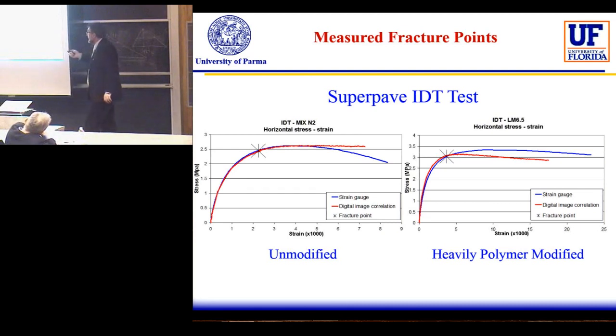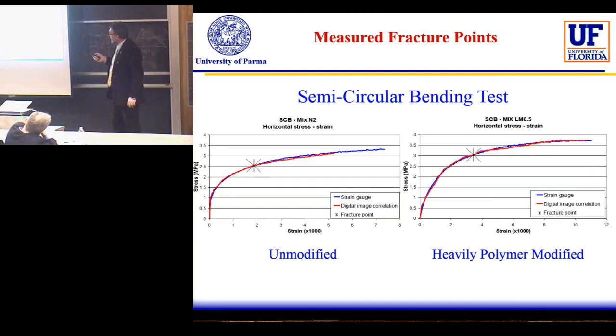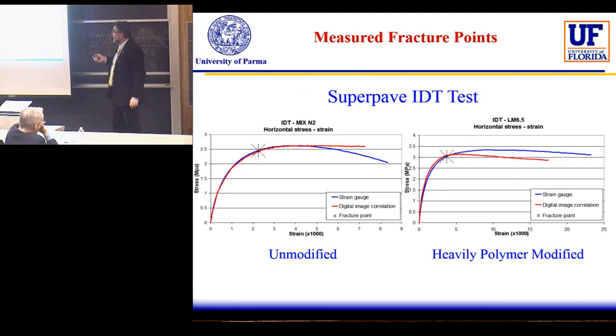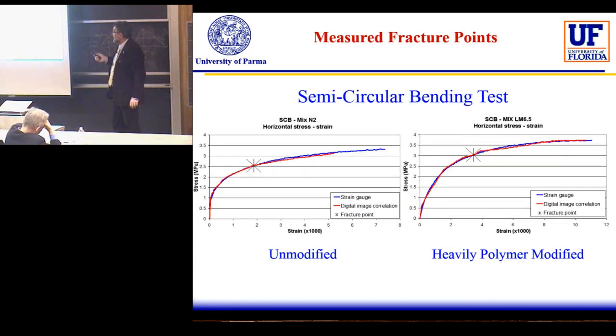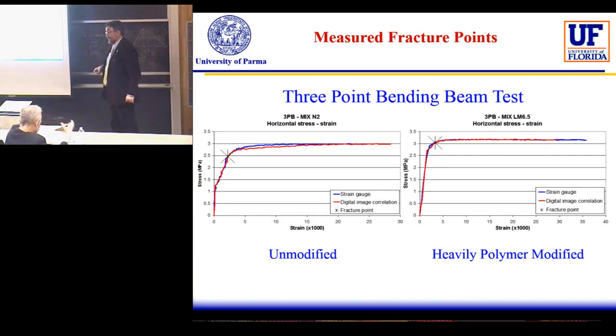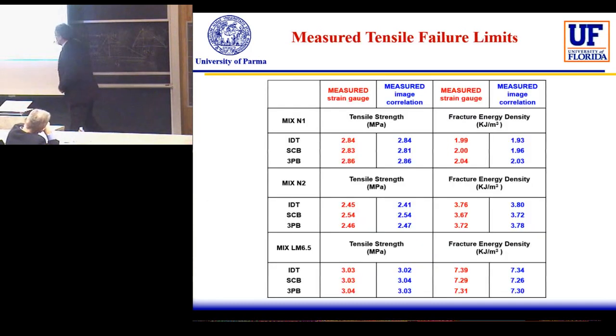And so we made an analysis on the test. Here is what happened with the Superpave IDT. Those are the results using the semicircular bending test, so a different geometry. And here, the 3-point bending test. Looking at the results, we were able to see that the tensile strength doesn't allow a clear differentiation of the different materials, because we see that IDT, SCB, everything gives more or less the same result.